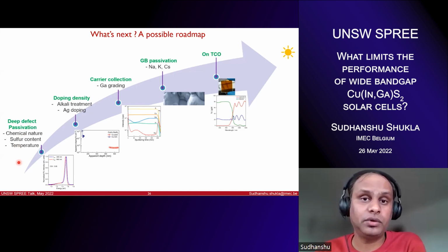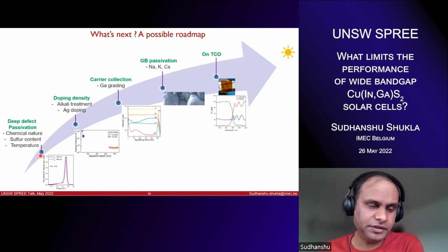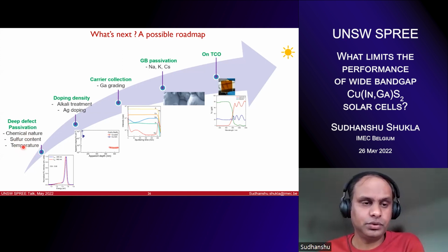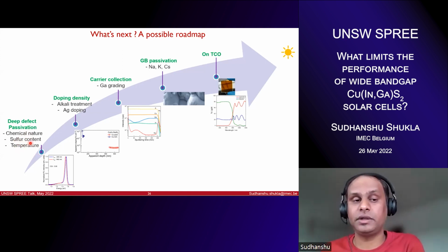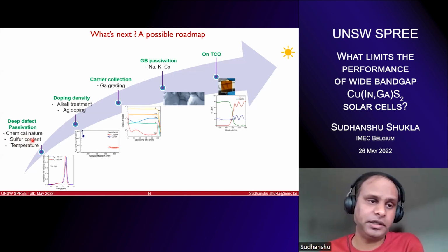There is much more going on, and that needs to be quantified experimentally through some complementary techniques. So this should be the first step. And some things that we could try is playing with the sulfur content, because you saw the sulfur vacancy also has a very low formation energy, defect formation energy. It is indeed playing a role.